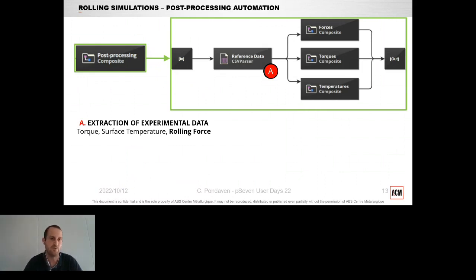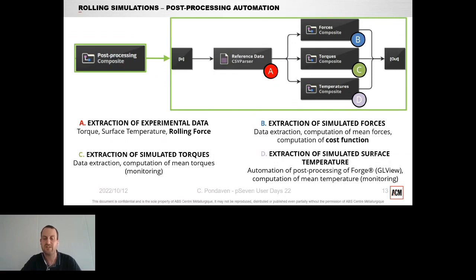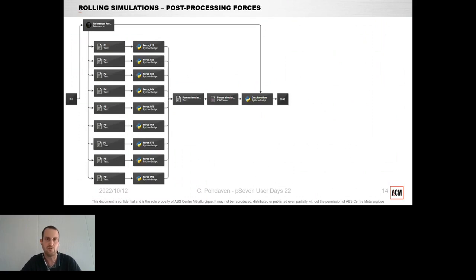and we classify them in terms of torque, surface temperature, and rolling force used for the optimization. And then for each computed value, we use the post-processing to compute the mean of each value computed by the model. And we have a specific approach for the temperature, where we have an automation of the post-processing software of Forge, GLView, to compute the surface temperature and calculate the mean so as to monitor the temperature during the optimization phase. So we focus here on the extraction of simulated force that will be used to compute the cost function used in the optimization procedure.